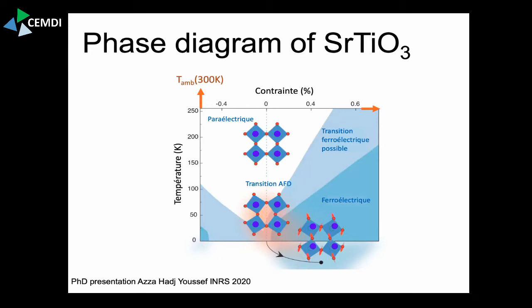That's an advantage of Raman spectroscopy over, for example, X-ray. X-ray would show you the final result, but Raman spectroscopy can already tell you by the change of vibrational frequency that such a transition is possibly coming, that your system becomes susceptible for this kind of transition, even though it doesn't quite go there yet. So you get a bit more information on that.